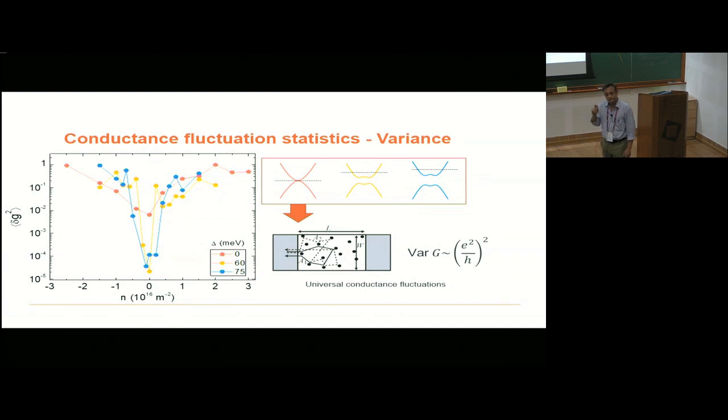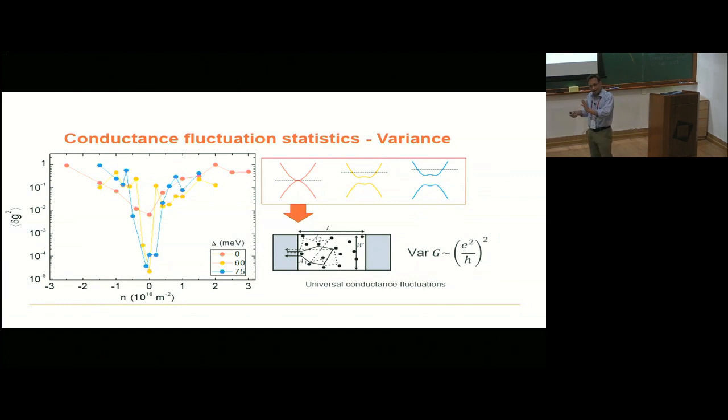Which one? This one? Well, yes, it will depend on temperature through the phase breaking length. If your temperature becomes so high that the phase breaking length becomes too small compared to the system size, that's when the temperature starts affecting. But at all the temperatures that we have looked at here, the phase breaking length is usually as long as the system size itself. So that's why the temperature dependence is very weak in most of our experiments.